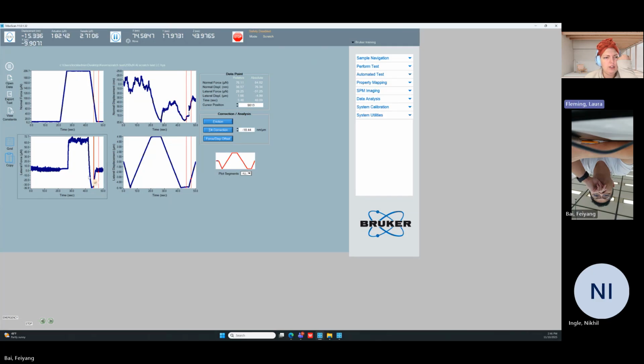So during the unload, our lateral force went negative. So instead of going down to the sample, it went up. So it seems like it bounced up and off some buildup in the sample, right? If we're scratching and we're building up any sample, any debris, then as it's unloading, it looks like maybe it popped up and out, or maybe it was a little stuck, actually. Aluminum, like I said, is pretty sticky. And you can see this here. This is not a great example, but sometimes